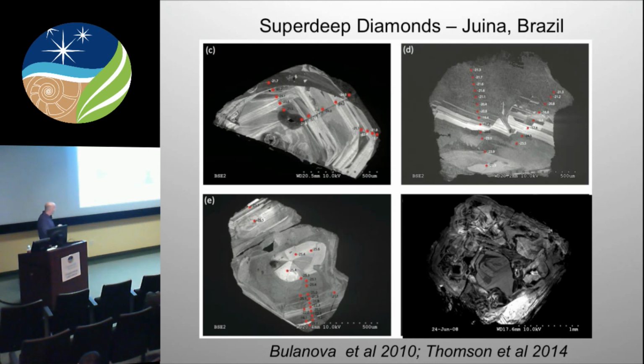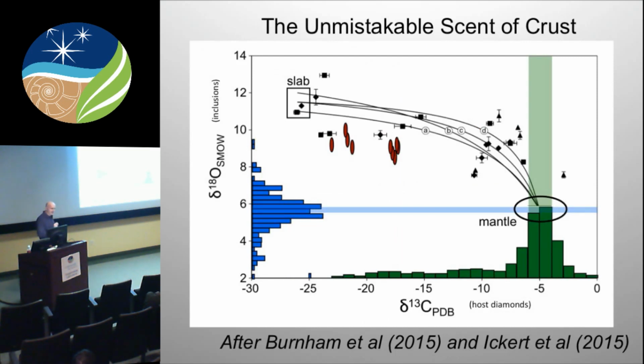In this case, what we're looking at is the delta C13 of the diamonds. Again, here's the normal mantle population for diamonds. And we're looking at the oxygen isotopic composition of the inclusions in those diamonds at the same time. And that's what's shown on the y-axis here, delta O18 relative to SMOW. And again, this is what you get for inclusions in lithospheric diamonds from normal cratonic lithosphere.